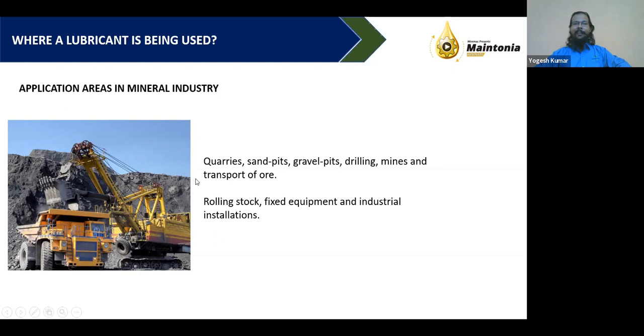An important point for steel and coal mining: carbon content in oil testing may show a higher value. The common assumption is that high carbon means the oil has oxidized — but this may not be true. In a coal mine, carbon particles enter the oil through the breather from the atmosphere, not from oil oxidation.